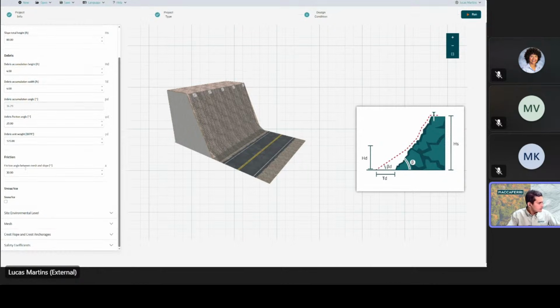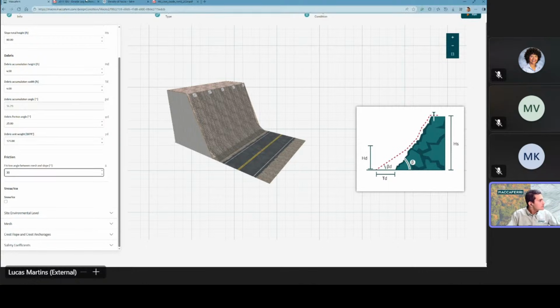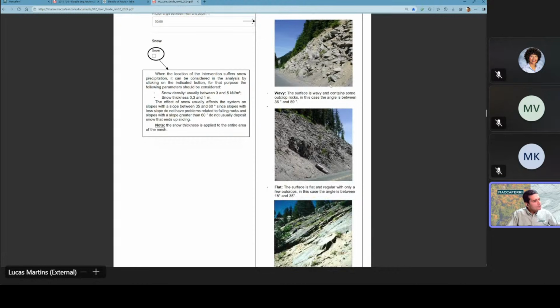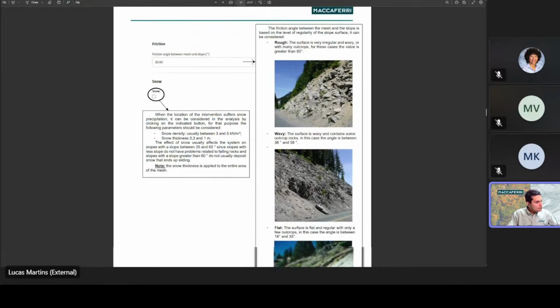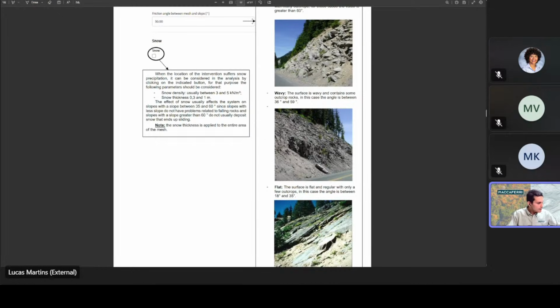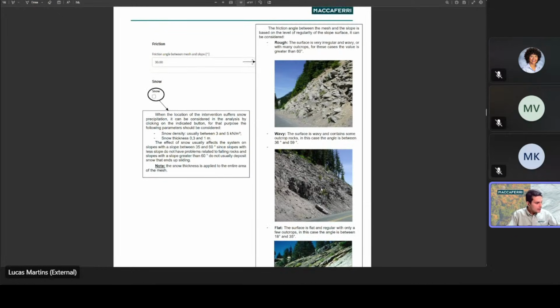Now here we have a parameter that's a little trickier. Friction angle between mesh and slope. This friction angle has to do with the undulation and asperity of your slope against the mesh. This input is more sensitive in applications where you have snow weight on top of that mesh that creates a bigger friction load. This comes straight out of the Washington guidelines. And if we go down here, you see that you have a few photos as guiding you. So you would use an angle between 18 and 35 for a flat slope, 36 and 59 for a wavy slope, and above 60 for a very rough slope.